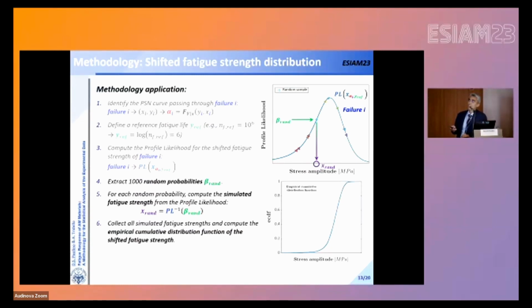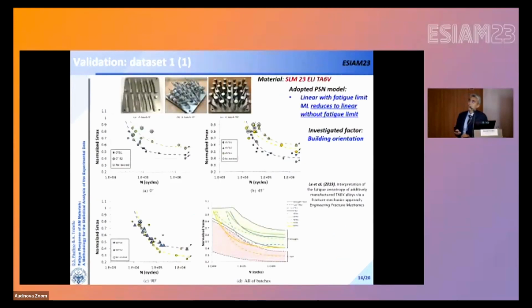So a random extraction of a number of probabilities, then a random assessment of the fatigue strength according to the profile likelihood function, and then collect all the randomly extracted fatigue strengths to get the fatigue strength distribution. So all these passages are applied to get this relevant information: the fatigue strength distribution for a defined fatigue life, which takes into account the uncertainty in the estimation and the data set that is collected in the experimental tests.